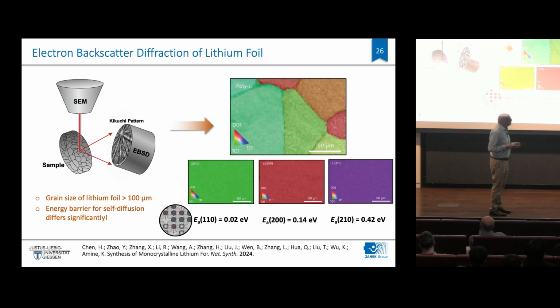And this is when we had published our first paper. There was a very nice paper coming up from Argonne National Lab with Khalil Amin and others, where they showed surface images. So what you see here is a lithium sample, and they got just a surface image. They got their so-called Kikuchi pattern, which contains all the information on the lattice, and then the color code simply says this is specific for a certain orientation of your grains. What you see here, they managed, in fact, to get huge grains, and even achieve virtually single crystalline lithium films. That's possible, but they only looked at the surface of the film and only post-mortem, so it was just a foil, essentially, at this point.